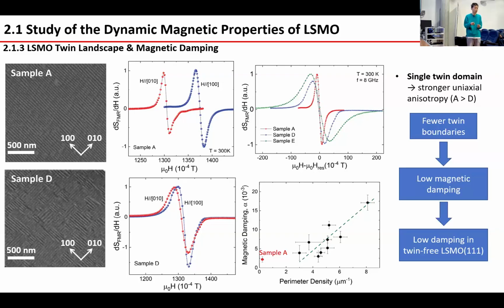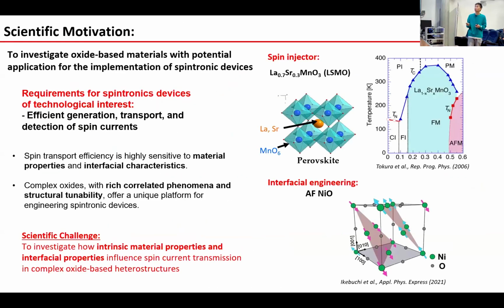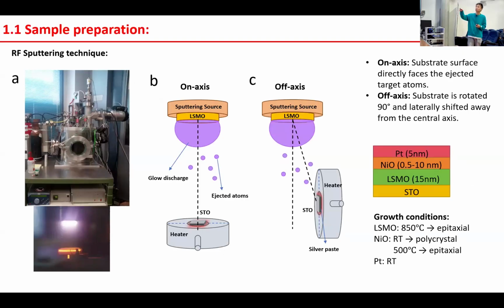Yes, initially, when I first grew LSMO, it had some segregation, or the roughness was really higher, or there were several particles. It depends on the growth parameters. We also optimized, as shown here. We put a lot of work into the optimization of the LSMO and utilized off-axis growth to achieve better DC magnetic property, and especially used silver paste applied very thin at the interface to reach better thermal conduction. But the silver paste is only for better thermal contact between the heater and the substrate, right? In this case, yes.